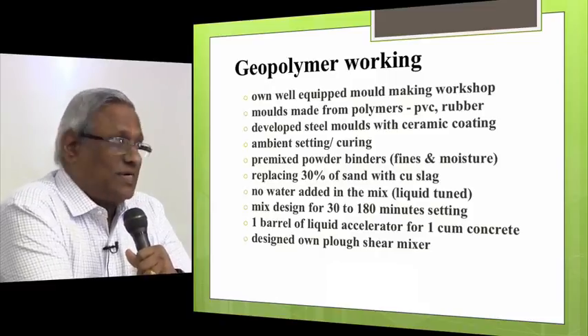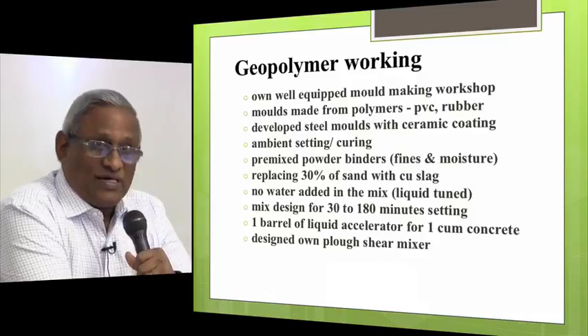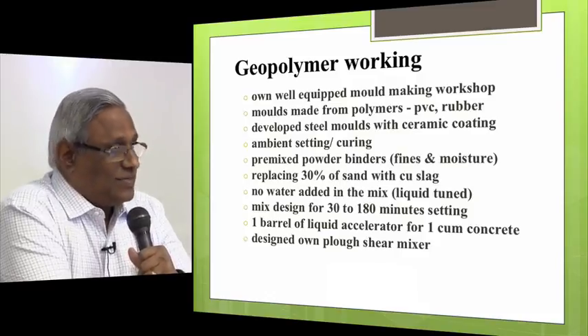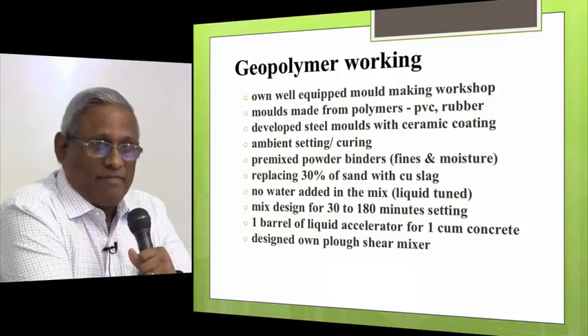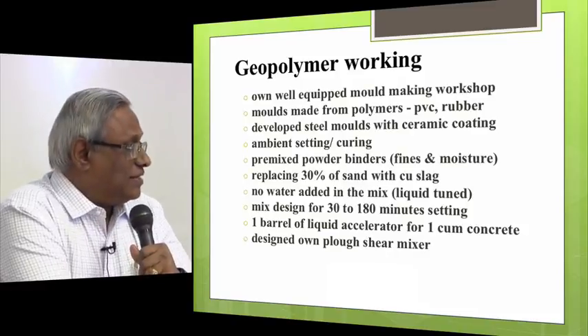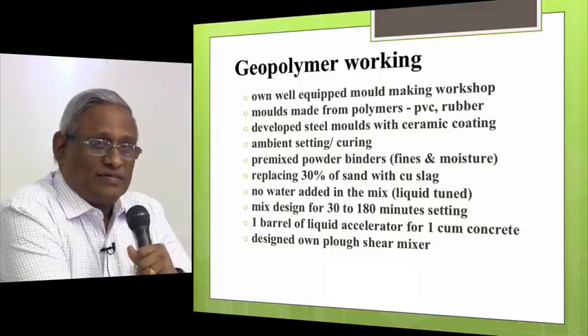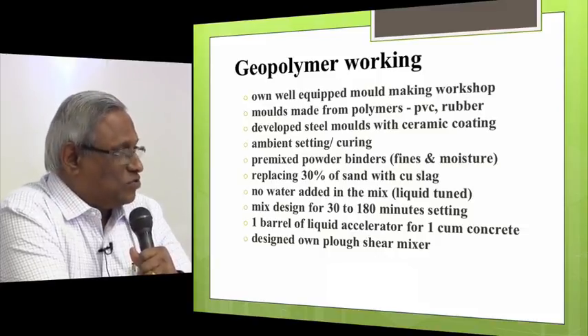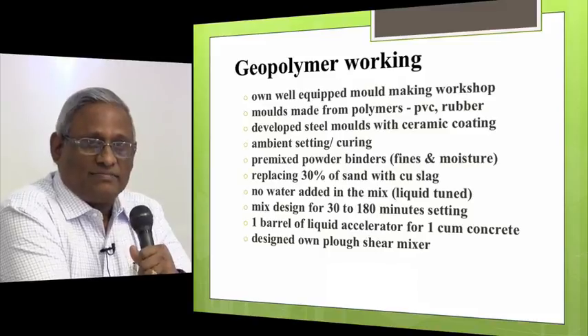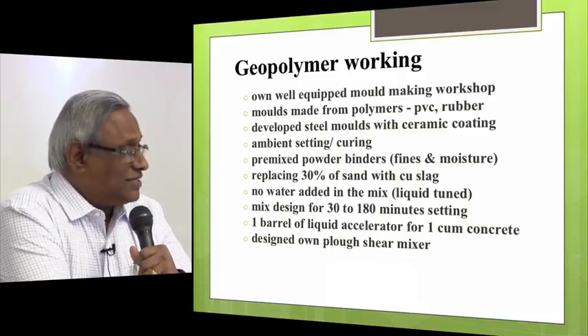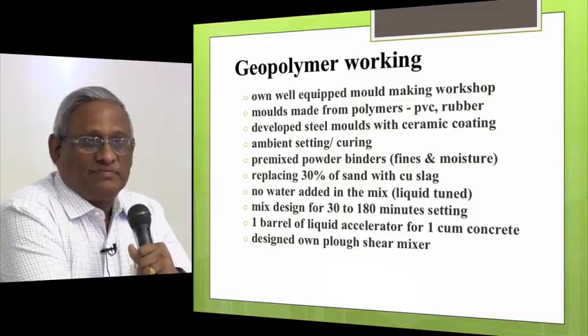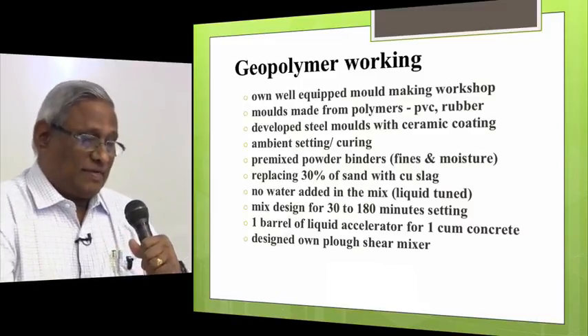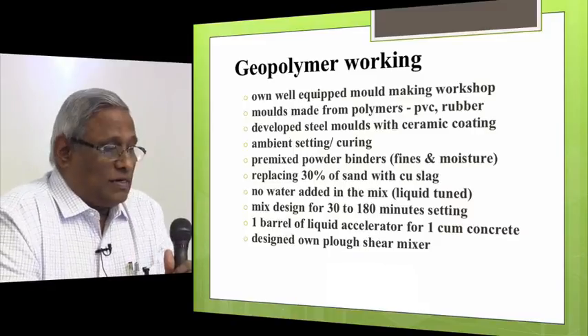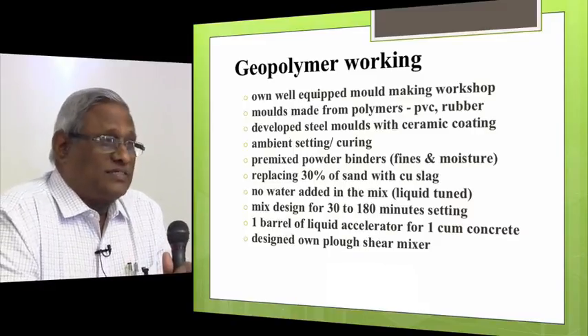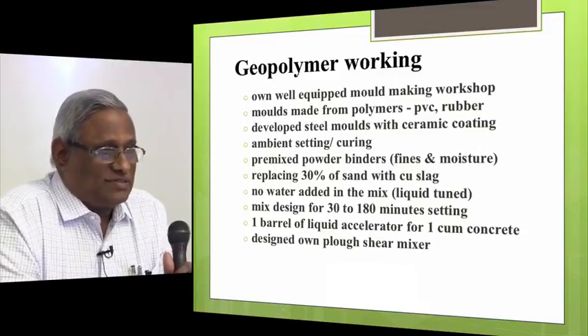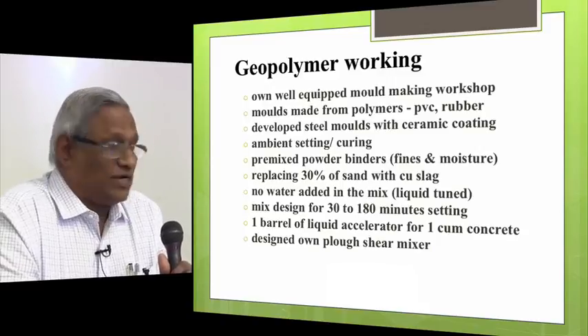These steel molds are ceramic coated. We have also done a Teflon coating, which works very well, but we are not able to recycle it for a longer time. We also did an epoxy coating, which also worked well, but again, the problem of recycling the molds. The ceramic coating lasts longer, so we have established a ceramic coating setup. We have an excellent ceramic coating setup because we need to do a lot of molds. It's a plasma coating. All our products are set and cured at ambient temperature. We have not done any elevated curing at all.